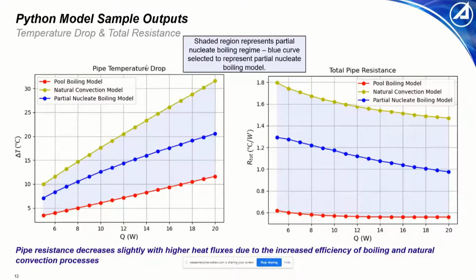For the purpose of comparison to experimental data, we selected the blue curve, which is based on the Rohsenow boiling correlation. But partial nucleate boiling behavior can really occur in that whole shaded region between the top and bottom curves. And then our least efficient form of heat transfer is just pure natural convection occurring along the evaporator wall due to the temperature gradient and the working fluid being in a pool. So that results in the highest resistance and also the highest temperature drop.